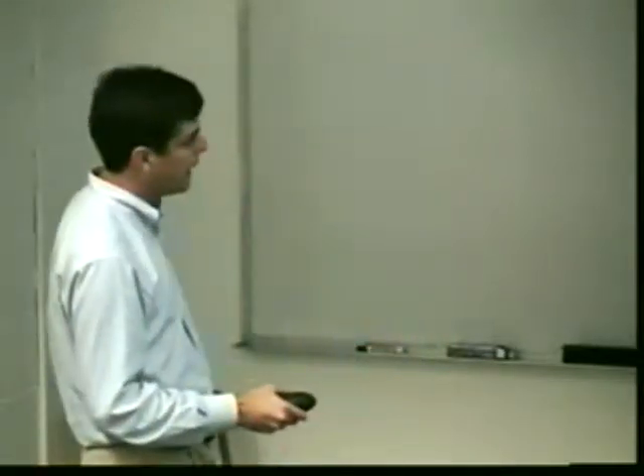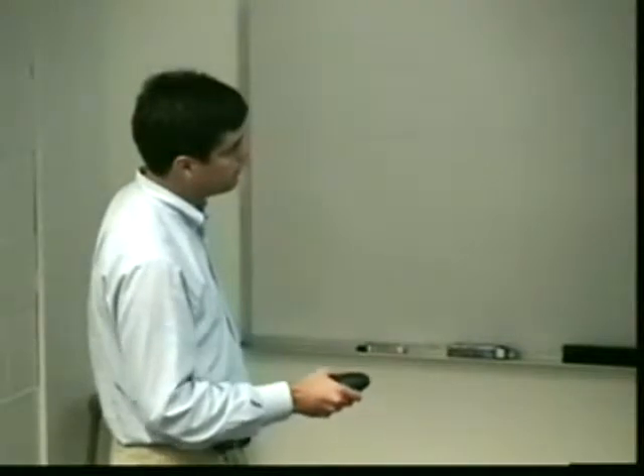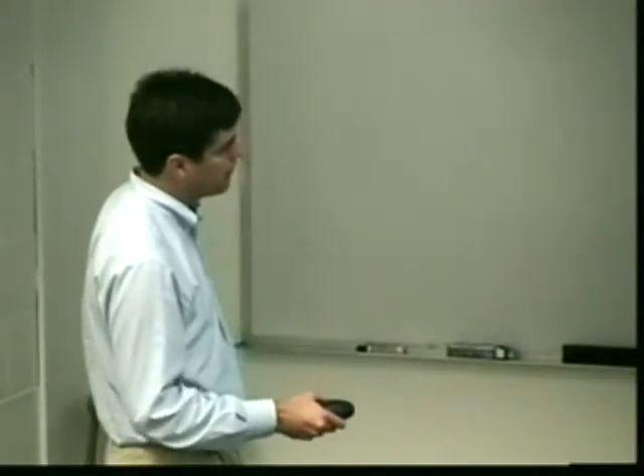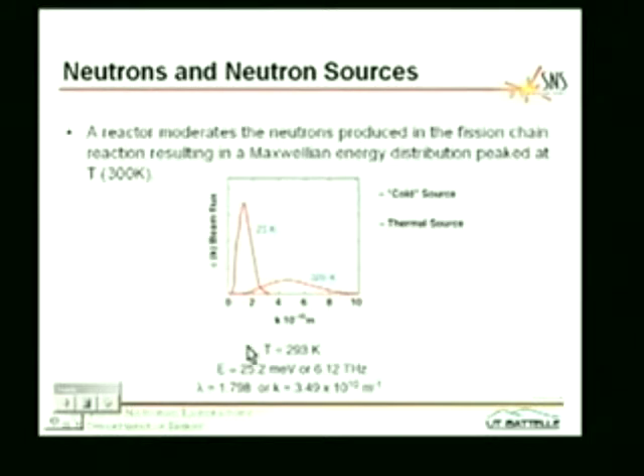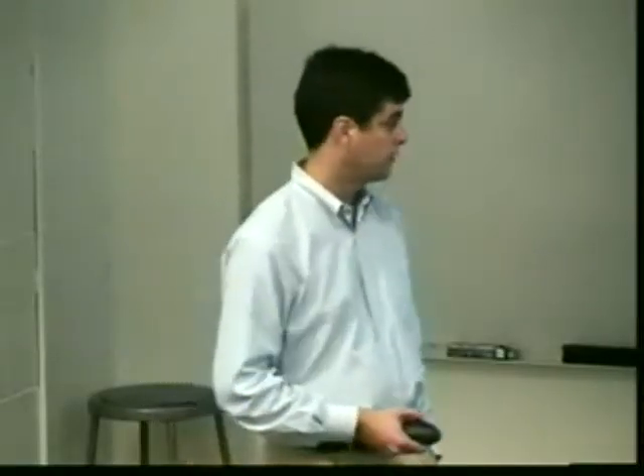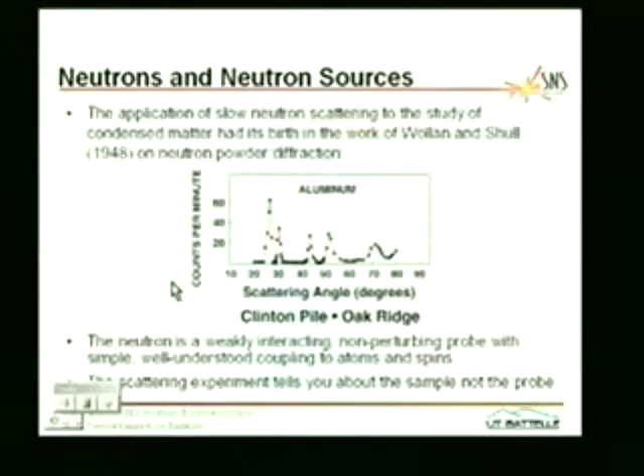Of course, you can play games and, for example, introduce a cold source into your reactor, which would be an aluminum can filled with supercritical hydrogen or deuterium. And that has the effect of shifting the Maxwellian down to lower temperatures or energies and longer wavelengths. And in fact, that's quite productively employed in cases where people want to study materials that have structural features on longer length scales and therefore longer wavelength neutrons.